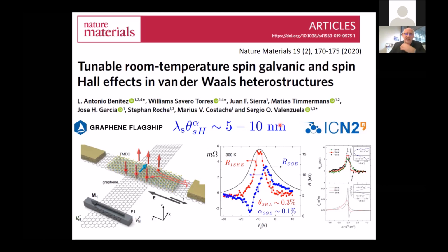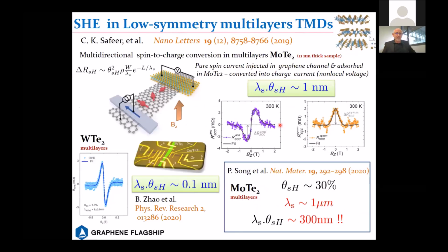So this has been a very important achievement, because then we can start to use pure spin currents in this complex architecture. There has also been very recent activity on multilayered transition metal dichalcogenides, such as molybdenum ditelluride or tungsten ditelluride, here in the group by Roche. And they're also showing some very interesting spin transport properties and spin active properties. There was a result last year in Singapore which was very puzzling, because they not only reported a very large spin Hall angle, but they also estimated an enormous spin diffusion length in such a strong spin-orbit coupling material, resulting in a figure of merit which would be completely unprecedented.